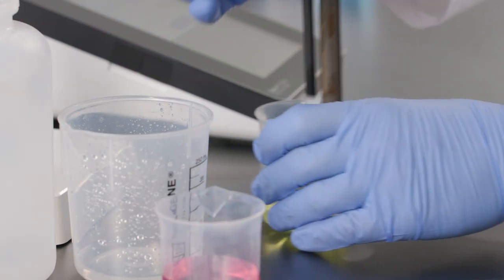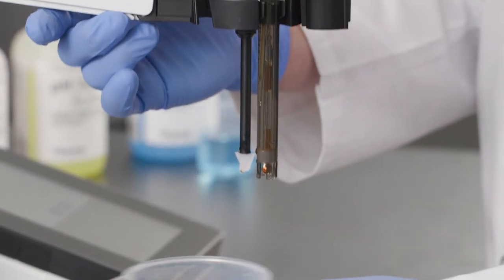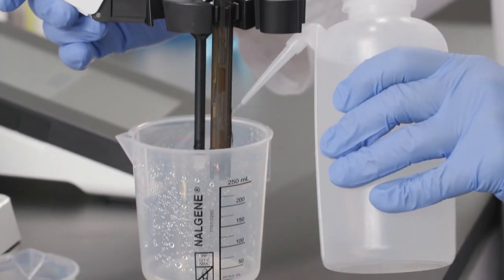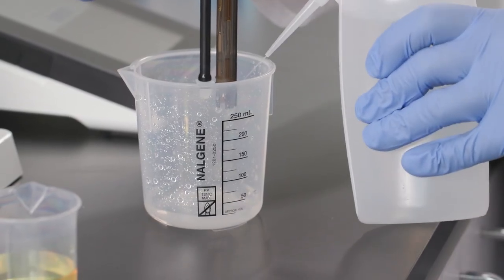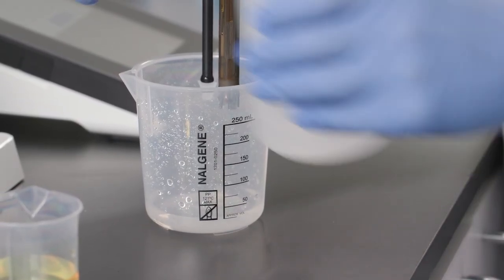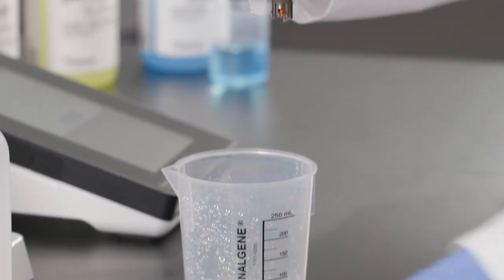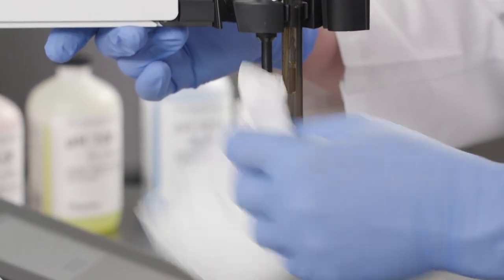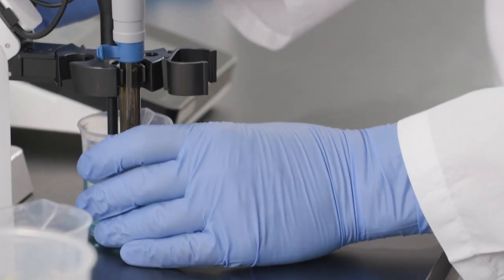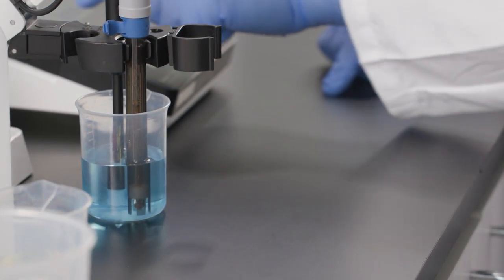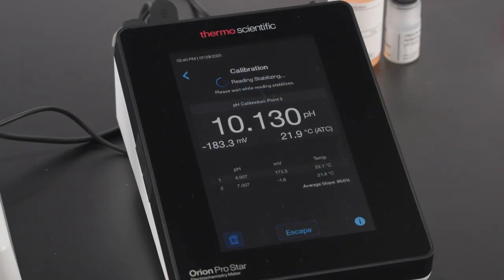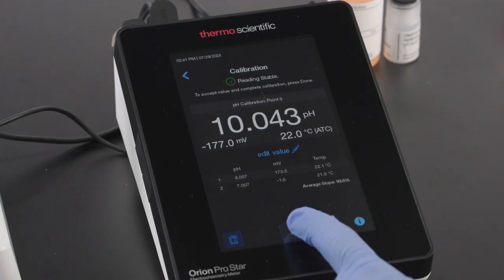We should note at this point that temperature measurement is an important component for accuracy. During calibration, temperature readings are used to assign the correct, accurate pH values to the calibration buffers. For example, a pH 10 buffer has a known value of 10.01 at a temperature of 25 degrees Celsius, but has a known value of 10.06 at 20 degrees Celsius. When measuring samples, temperature readings allow the meter to stay in calibration by adjusting the calibration to match the sample temperature. The meter has recognized pH 10 and it's displaying the known value at this temperature. You can accept the results of the third calibration point and complete the calibration by tapping the Done button.